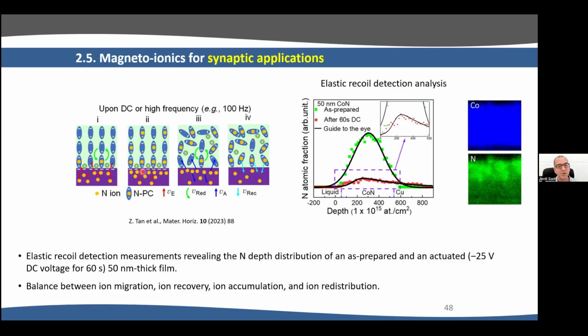When this happens, the nitrogen cannot be further released to the liquid because we are exceeding the solubility limit, and we need to stop the voltage for new propylene carbonate chains to reach the interface and then take some additional nitrogen from the film, and then this allows us to increase the magnetization further. So the fact that sometimes we see nitrogen at the top of the film is because when we go very fast, this nitrogen cannot be further released, and then we see it at the top. So basically, nitrogen at the top is a signature of fast magnetoionics, nitrogen at the bottom, slow magnetoionics.